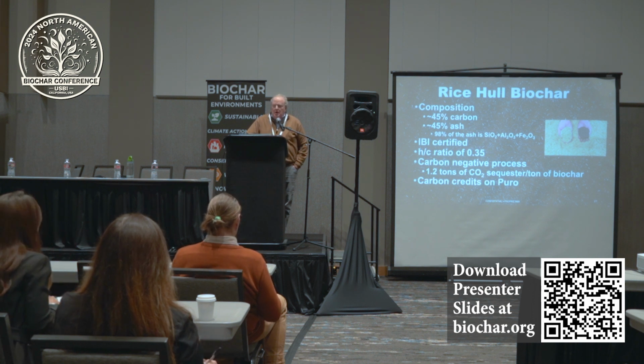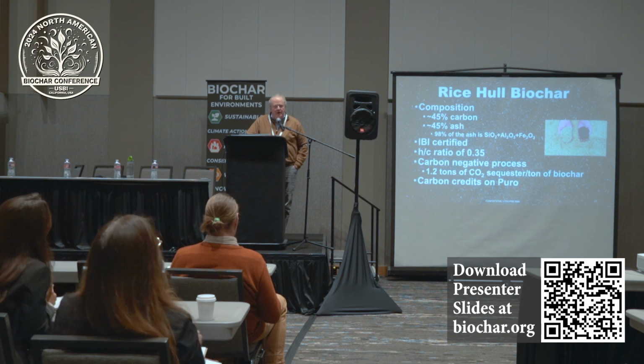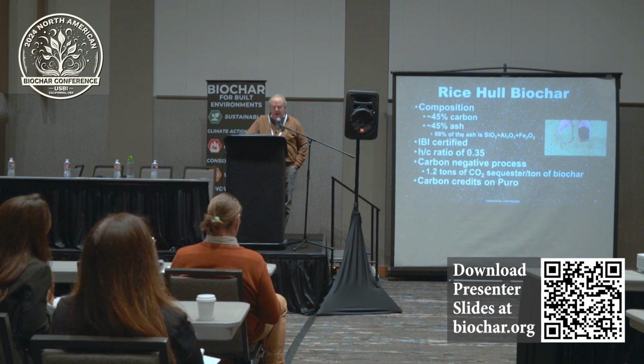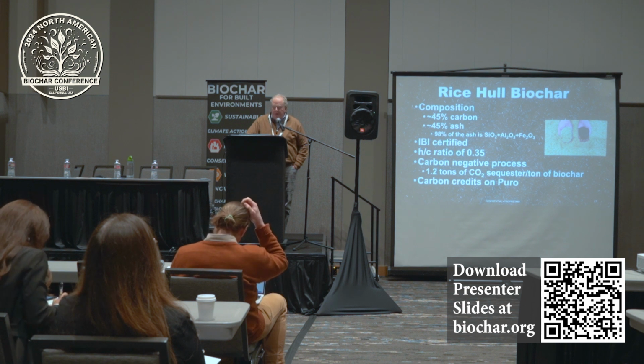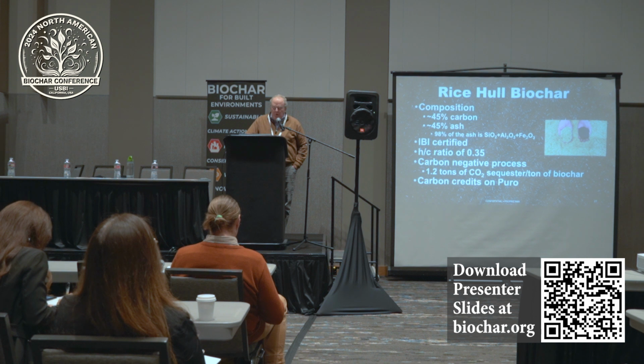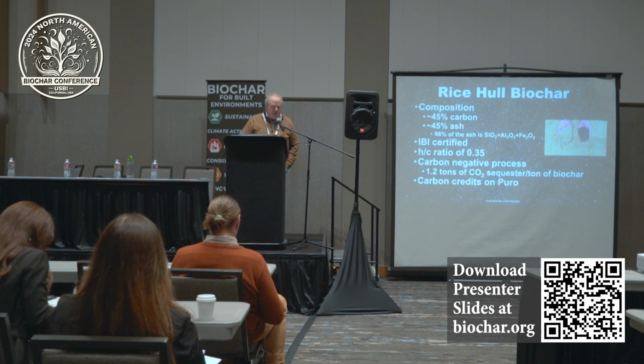So for us, our biochar is roughly 45% carbon, 45% ash. Most of that is the silica dioxide. We are IBI certified. We've got a low hydrogen carbon ratio. And because of the high ash content, we're at about 1.2 tons of CO2 sequestration for every ton of biochar we make.